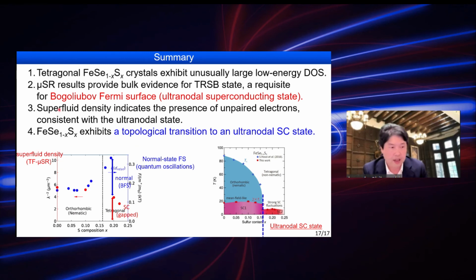And superfluid density, measured by transverse field μSR measurements, indicates the presence of unpaired electrons consistent with the ultranodal state. Finally, iron selenium sulfur exhibits a topological transition to an ultranodal superconducting state like this.